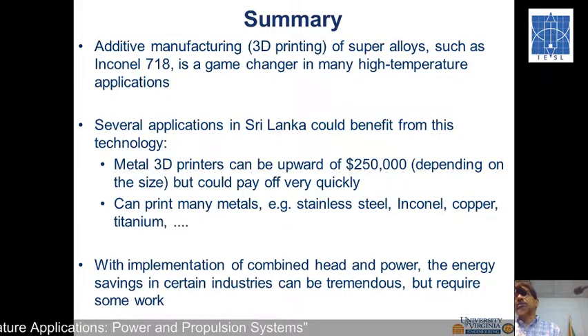The issue is that sometimes they have porosity, so structural issues, which can be a defect, especially on these turbines working at very high temperature, with associated cooling rates as well. If it is not properly done, yes, absolutely. This is why the aircraft industry is very cautious about it. They don't want the blade to break off.